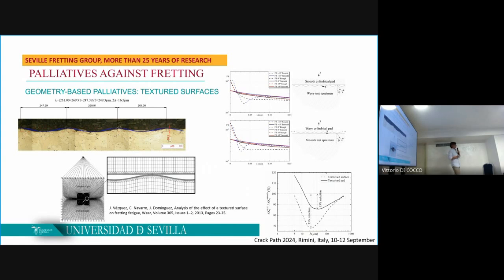Also, we have worked with another type of geometry-based palliative. In this case, we have worked with wavy surface. But in this type of wavy surface, we try to resemble the waviness produced by shock peening in the surface. We analyze two cases. The first case is the waviness is introduced in the test specimen, and in the second case, the waviness is introduced in the pad.